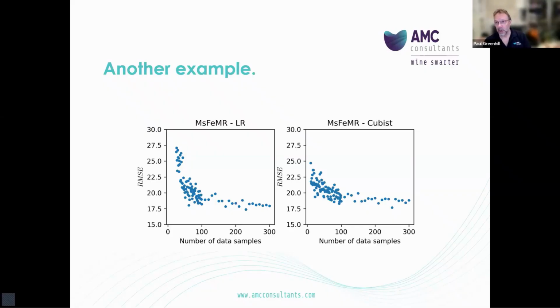So in a second example, this is a set of recovery data using the same two predictive model algorithms, a linear regression and a cubist model. And we've again plotted the same values from the error estimation against the number of samples used to train the model. So you can see again, and this is a recovery prediction. The previous data was a prediction of a hardness parameter, drop weight index. You can see that it has similar characteristics.